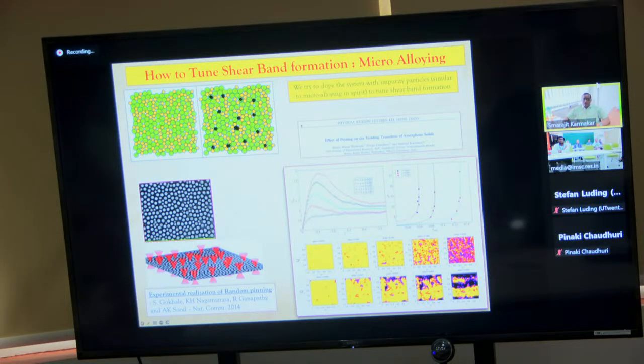And what we found, which is displayed, I hope you can see my mouse in this panel, where we plot stress versus strain. You see that when you increase the degree of pinning or the pinning concentrations, then the material becomes much stronger. The modulus goes up significantly. The stress peak goes up, but the peak becomes broad as well. And also notice that the yield point shifts to larger strain. So the system was able to support much more than usual non-pinned glasses.